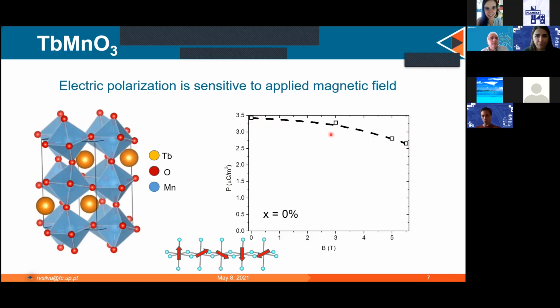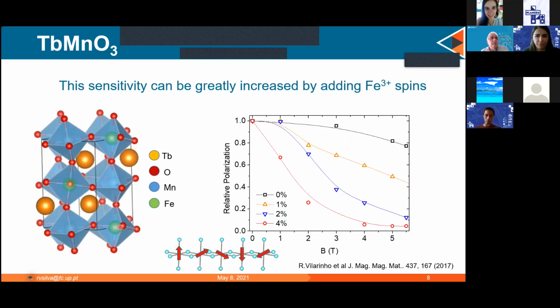It has an interesting effect which rotates from one direction to the other, but the overall value is actually quite constant. And what we found out in our group is that if you substitute some of these manganese spins by iron spins, the iron spins are much more sensitive to the magnetic field. And now when you put 1, 2, or 4% of iron, it becomes so sensitive to the applied magnetic field that you can actually turn on and off the electric polarization at low temperatures using somewhat high magnetic fields.